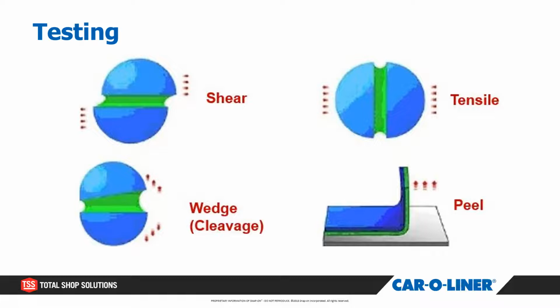So when you look at a technical data sheet and you see a lap shear test, or a tensile strength test, or a wedge or T-peel test, when you look at the upper left there, the shear is just a test where it's pulling itself across the joint, measuring the shear force it takes to break that bond when you're pulling it apart. I want to say horizontally there, but the test's usually done up and down. But again, you can see which way the direction is being tested. Tensile is like a tug of war, right? You're just going to pull it apart and see how well it sticks to itself. And that's the tensile strength of an adhesive.